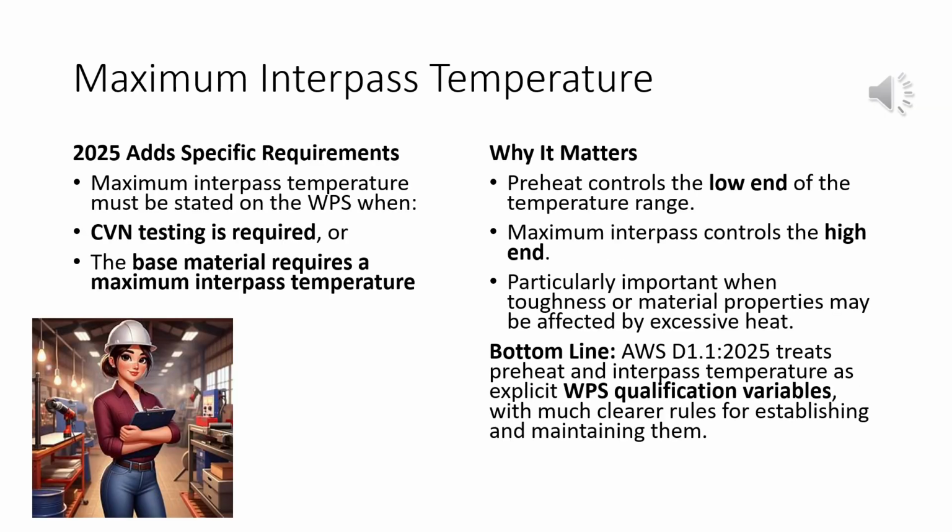Maximum interpass temperature. Now let's look at the other end of the temperature range. The 2025 edition specifically addresses maximum interpass temperature. A maximum interpass temperature has to be stated on the WPS when CVN testing is required or when the particular base material requires a maximum interpass temperature.